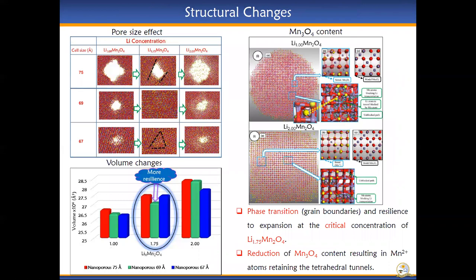The structural changes observed on the materials after the amorphization and recrystallization processes, amongst others, is the pore size effect, where increasing the lithium concentration from the pristine spinel to Li1.75 resulted in the pore reducing in size for nanoporous 75 with green boundaries and black dotted lines.